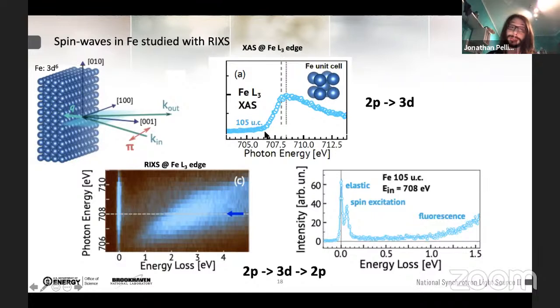So we fixed the incident energy across this absorption edge, and we measured what we observed as a function of energy loss. And here, in this left plot, I'm showing the incident energy on the vertical axis and the energy loss on the horizontal axis. And as color intensity, we have the intensity of our RIXS spectrum. And we can observe that at zero energy, we have an elastic line, and most of the signal goes into this broad hump, which is essentially fluorescence, which is pretty boring.